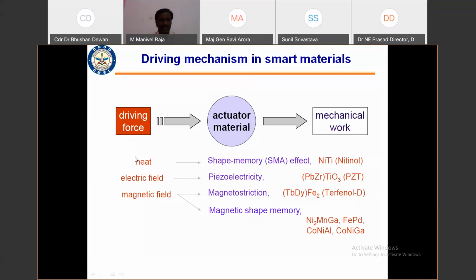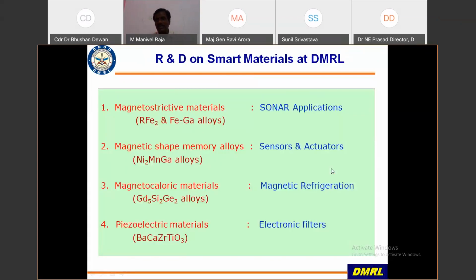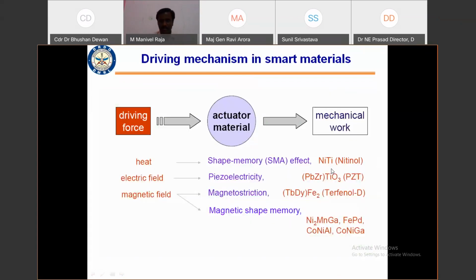So when you say heat, here the thermal energy is going to be a driving force. The example for that kind of shape memory smart material is shape memory alloy. It's basically nickel titanium. Nickel titanium changes its shape when you change the temperature, so you can actuate it. You can do the desired functions by simply changing the temperature.